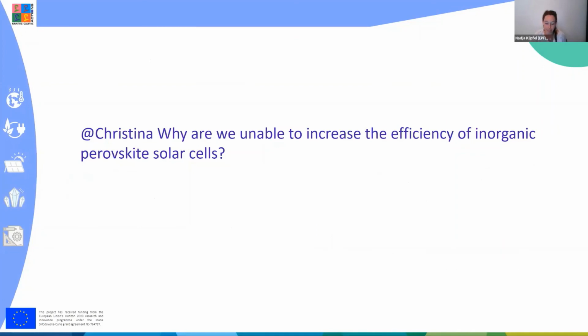So for Christina, there's another question. They're asking, why are we unable to increase the efficiency of inorganic perovskite solar cells? If you consider the lead-based cesium lead triiodide, theoretically you can have high efficiencies if you extract the calculated current from the absorption coefficient. However, cesium lead triiodide is quite unstable at room temperature, so due to this instability, its performance is quite poor. And if we go for lead-free perovskites like tin triiodide, then tin has other issues regarding stability, so again the efficiencies are quite low.